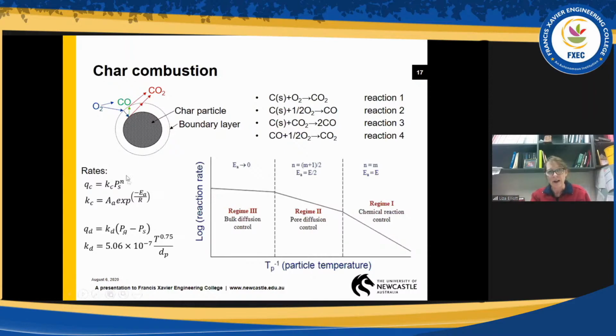Generally for coals, the activation energy here is about 150 kilojoules per mole, and that doesn't change too much at all. But for different coals, the pre-exponential factor really can change. Okay, the other point to make here is particle size really impacts where these boundaries occur between the changes. And so even though PCI occurs at temperatures that you would expect to fall up here, so pulverized coal injection into blast furnaces is what I'm talking about, you would expect them to occur up here because we're talking about the highest temperatures that we see in combustion. Because we're talking about very small particles, it's debatable whether they actually get into oxygen diffusion control, because the smaller the particle, as you can see down here, the higher the rate. So you have to be careful and don't assume it's solely particle temperature controlled.